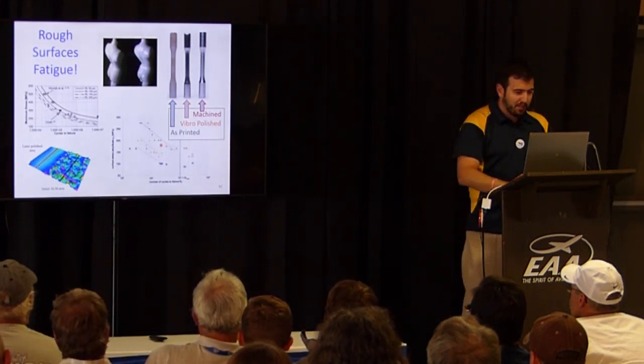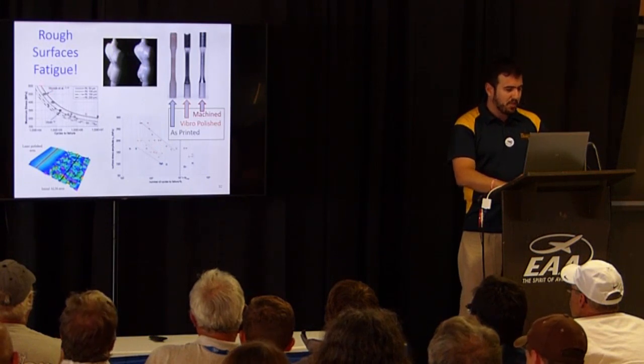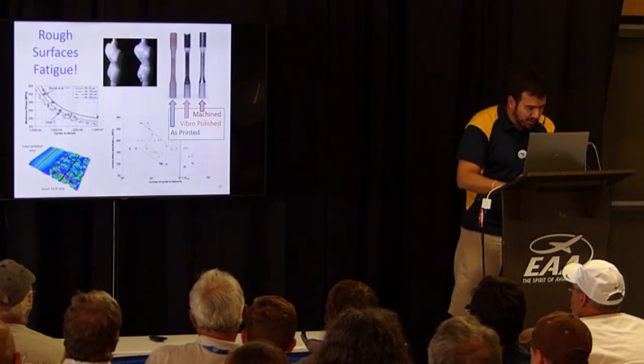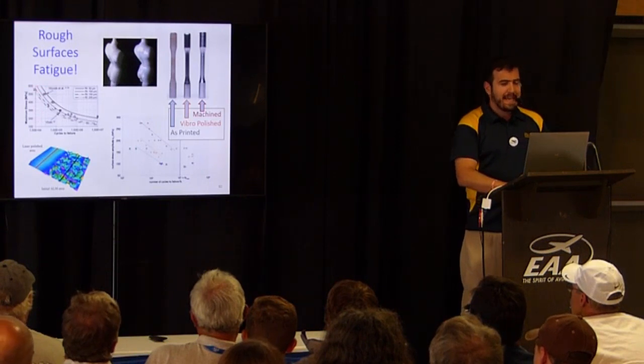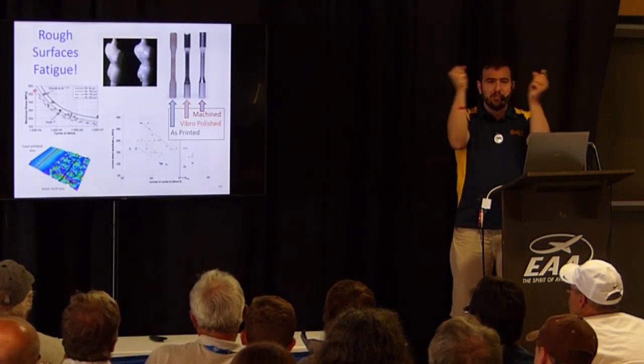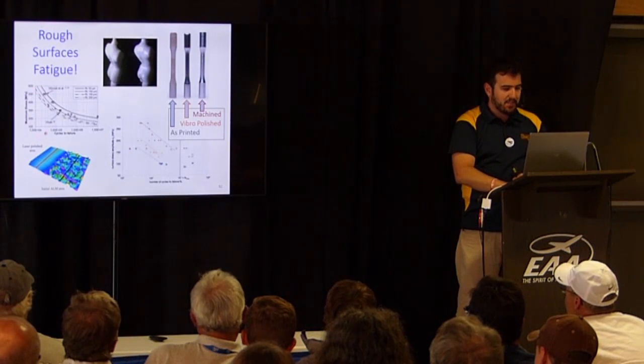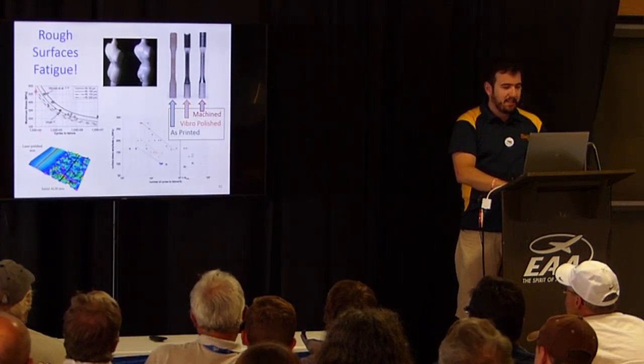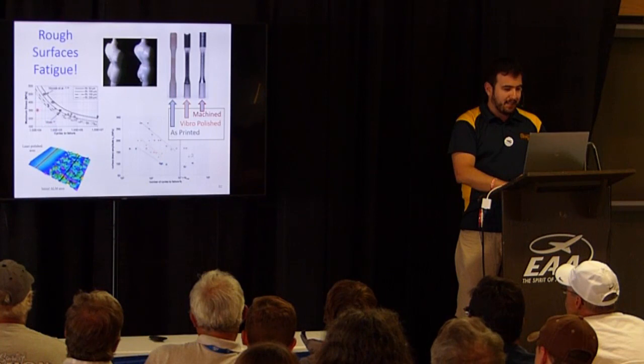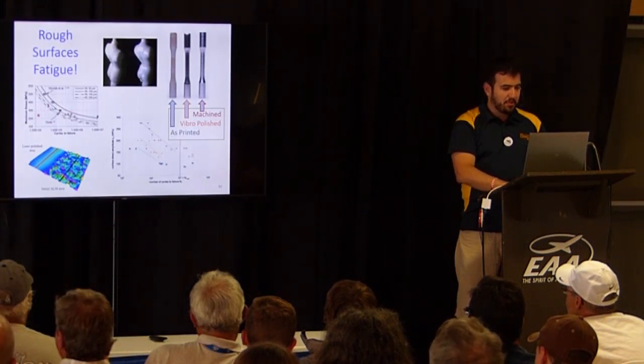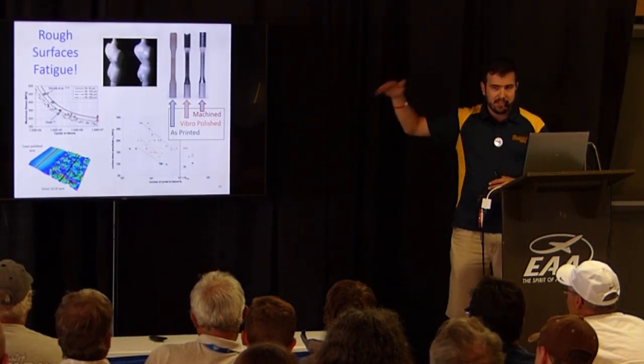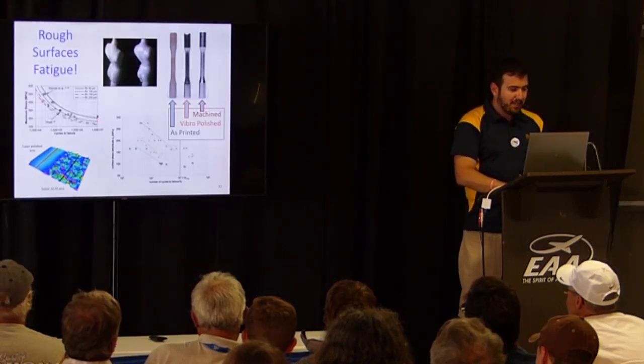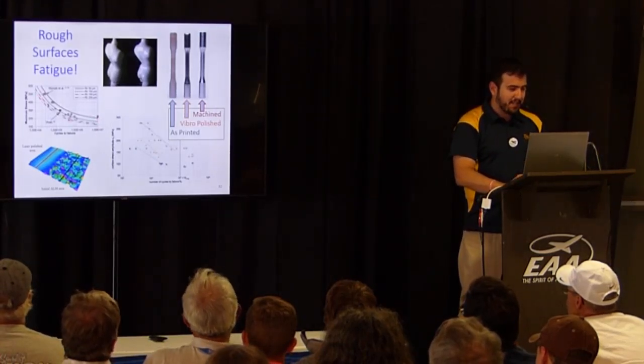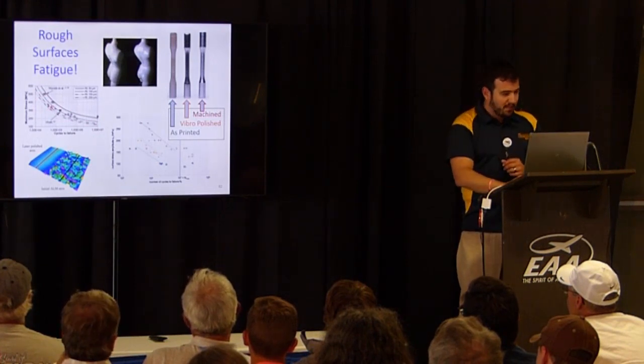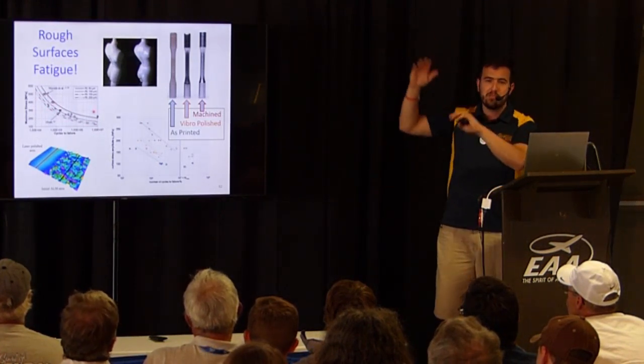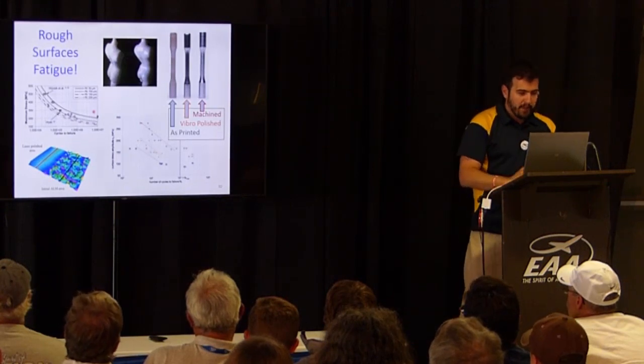So to give you a very quick introduction to fatigue here, most times you measure fatigue, you display what you measure in what we call an SN curve. So an SN curve, on the y-axis is how much you stress the thing every time, if you're doing a fatigue test like this. And the x-axis is how long it lasts, right? So if you stress it a lot, it doesn't last very long. If you stress it less, it lasts more time. And if you don't stress it very much, it can basically last forever. Anyways, that's what an SN curve is. So you can see how the rough material has this SN curve on the bottom, the dashed line, but then once you polish the surface, you have this SN curve, which means you can stress it more and it will last longer. And this really works, right?